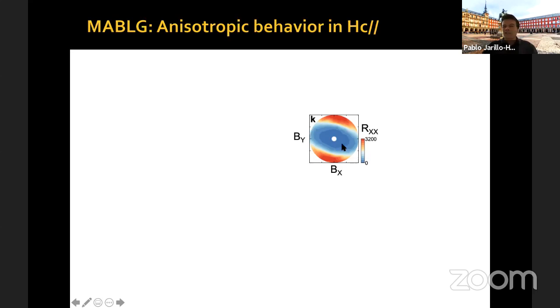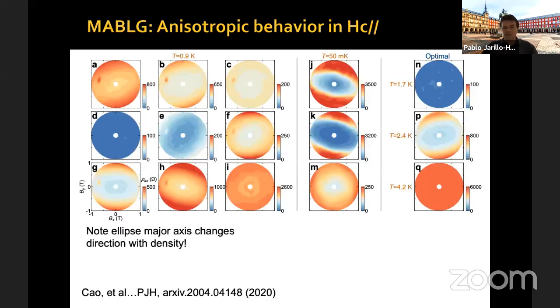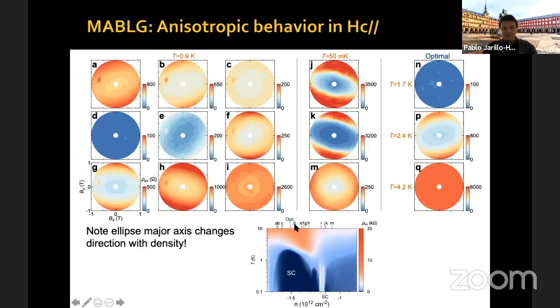And of course, this is for a particular doping, and we can measure this at a variety of dopings and at a variety of temperatures, okay? We have to do these measurements at varying temperatures and dopings because we have in our dilution refrigerator a vector magnet which allows us to apply in-plane magnetic field, but we have a maximum in-plane magnetic field of one Tesla that we can rotate. And for example, if you go to optimal doping, such as panel D here, which is close to optimal doping, you can see that within our one Tesla plane, the system is always superconducting, okay? We haven't reached the critical field in any direction.